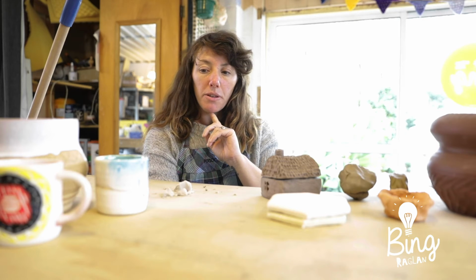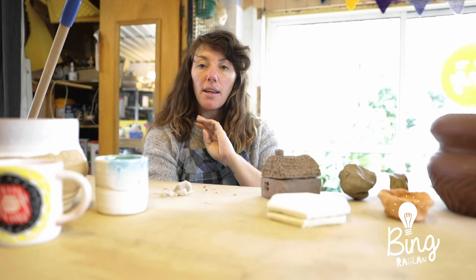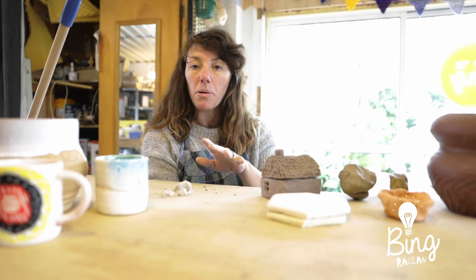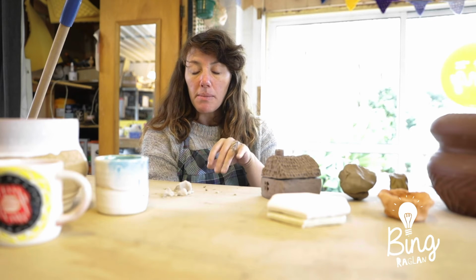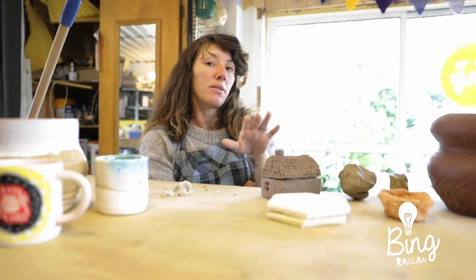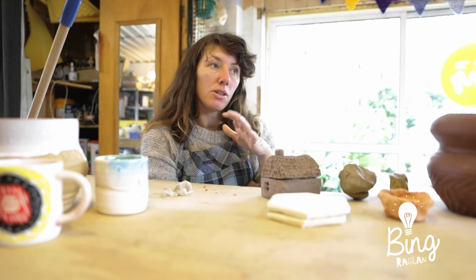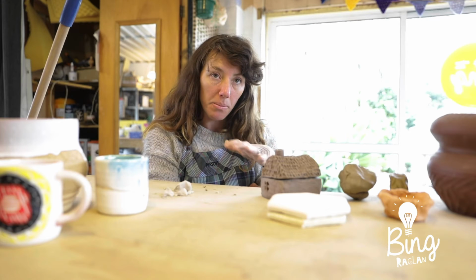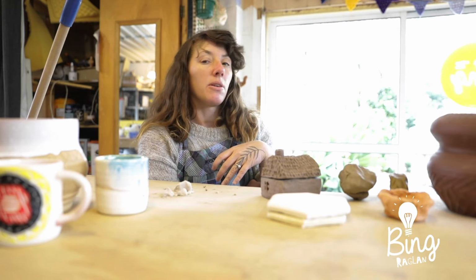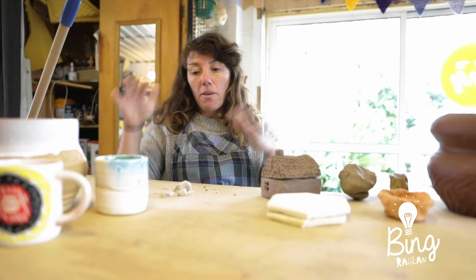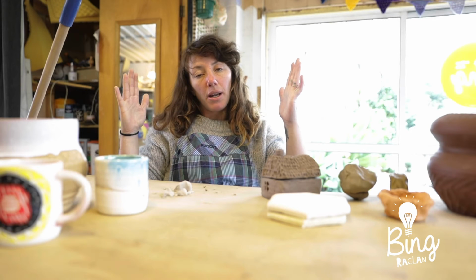So for a glaze firing it's very important that you don't have any glaze at all on the bottom of your pot. The glaze will melt onto the kiln shelves, and kiln shelves are very expensive, and you do not want to get glaze onto them, because if you get any on and you don't grind it off, it will start to eat into your shelf. Every time you fire it will eat deeper and deeper and deeper, and it will ruin your shelves. And for a kiln shelf about that size, you're looking at about $300.